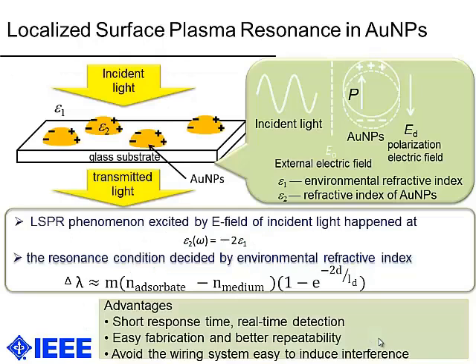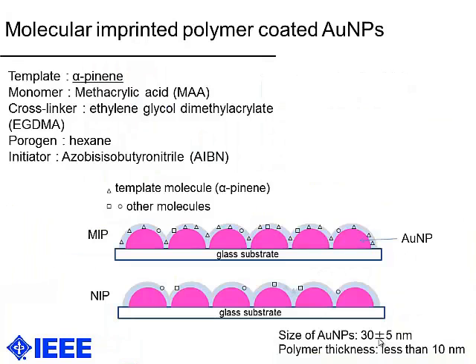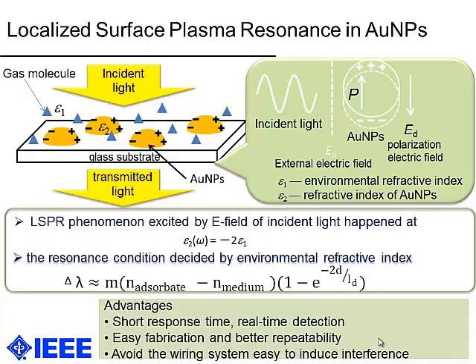And then this is the localized surface plasmon resonance in AuNPs. It's shown like this one. When some gas vapors are generated around the AuNPs sensors, the environmental refractive index of AuNPs will be changed. So here, the delta lambda shift will be changed. So by detecting this part, we can think that there are some gases generated around the AuNPs. And the advantages of this kind of sensor are the short response time, real-time detection, easy fabrication, and better repeatability, and also it can avoid the wiring system, which is easy to induce interference.